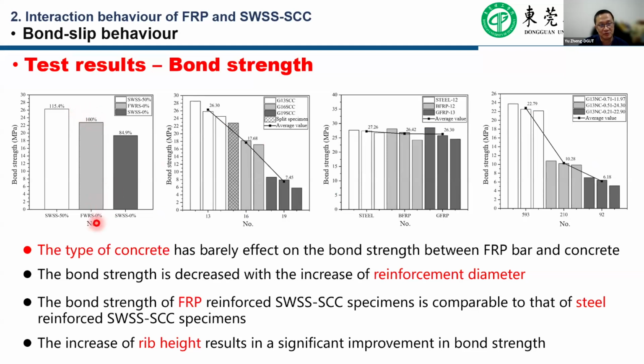And finally, we get some results. The type of concrete has a little effect on the bond strength between the FRP and concrete, but using the self-compacting concrete can improve the bond strength a bit. And the bond strength was decreased with the increasing of the reinforcement diameter. That has been reported widely. And the bond strength of FRP reinforced seawater and sea sand self-compacting concrete is comparable to the steel reinforced seawater and sea sand self-compacting concrete. And the increase of the rib height in the reinforcement has resulted in a significant improvement of the bond strength.